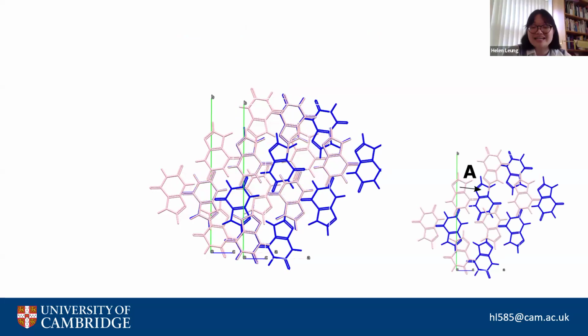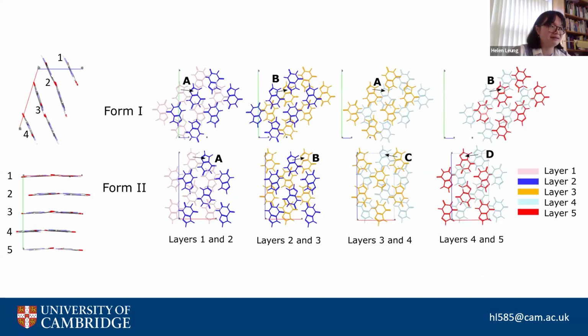And we call this translation A. And we repeated this with all of the layers for both forms of our xanthine polymorphs, of our polytypes. And the results are essentially here. So in form 1, you have a stacking sequence, essentially, which we call AB, AB, and that repeats, and that goes back to A. So it goes AB, AB, AB, AB.